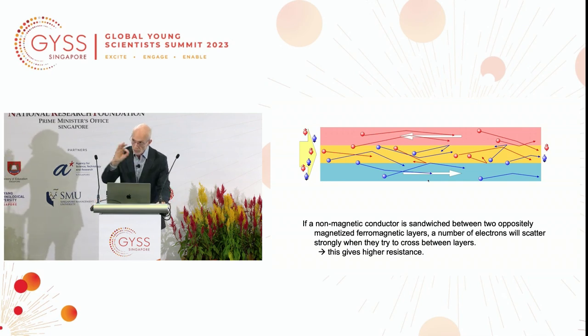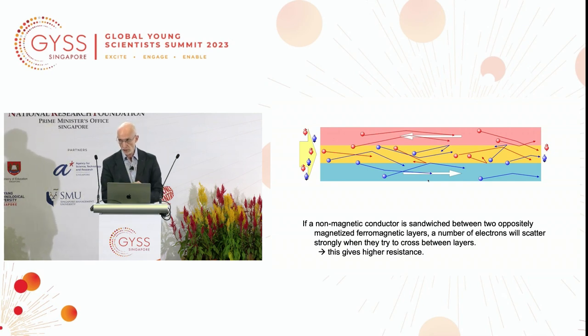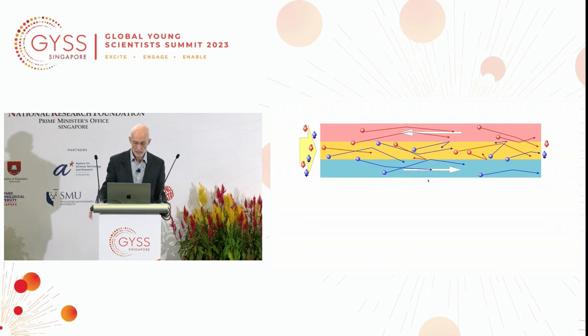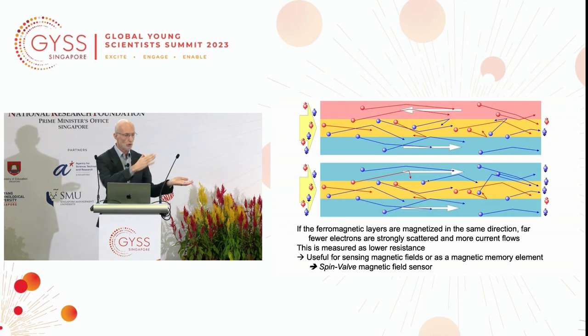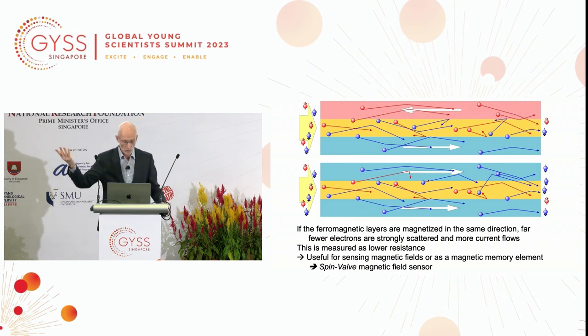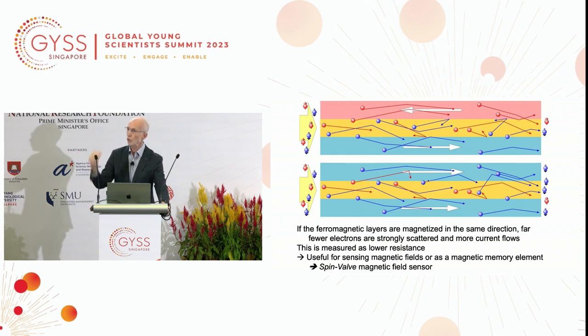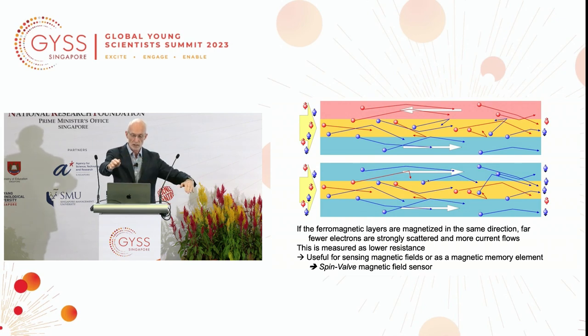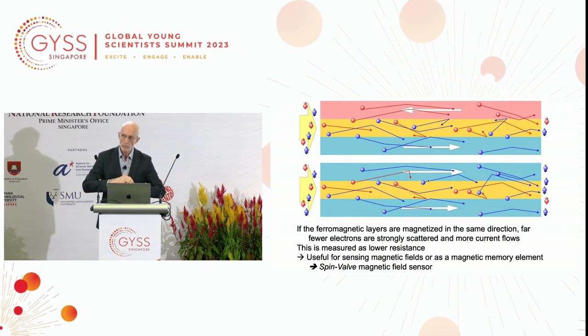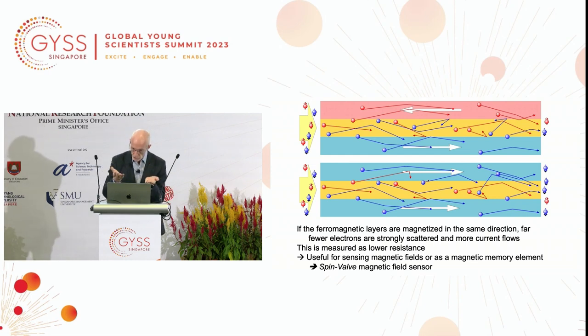However, the copper layer is so thin that the electrons will be moving in all directions, and the blue electrons will be scattered in the upper red layer, and vice versa. This means somewhere in this structure, all the electrons are strongly scattered. High resistance. Now, all we have to do is apply a magnetic field, rotate these magnetic layers which had anti-parallel magnetic moments to become parallel. Now the blue electrons can be short-circuited through this sandwich, and so the resistance is lowered. So basically, by applying a magnetic field, we can change the orientation of these atomically thin magnetic layers, and we change the resistance. This is a magnetoresistance phenomenon.